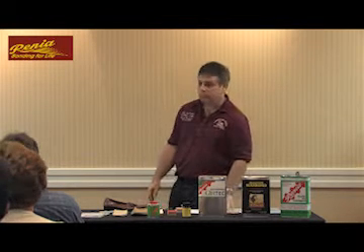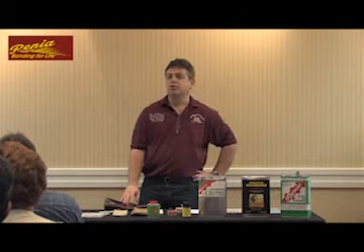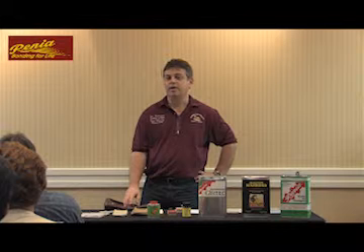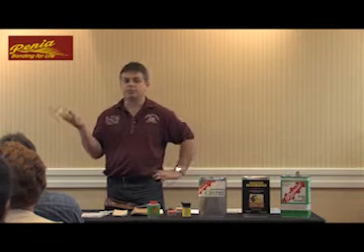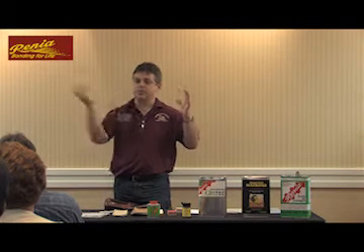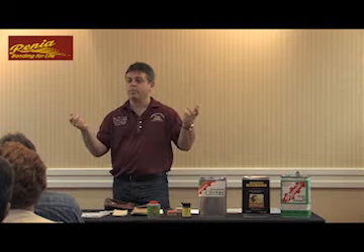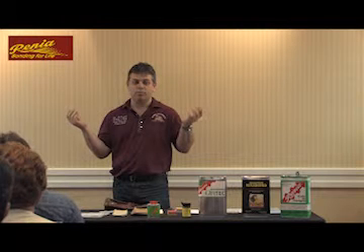Okay. You talked about heating up. Yeah, when you're doing a build-up or putting on a piece of crepe, you can. In a lot of shoe repair shops, we have what we call a convection oven, where the heat circulates through the oven really nicely, and we put the material in there and warm it up. I put mine on 350. Some might do a little less, some might do a little more.